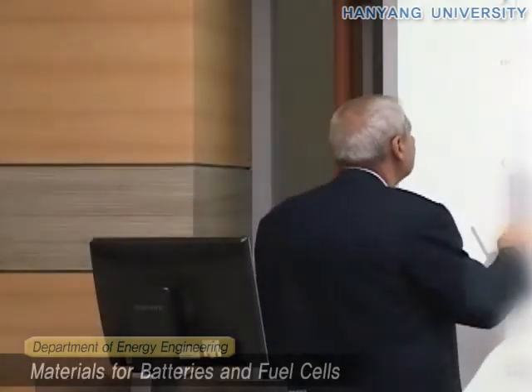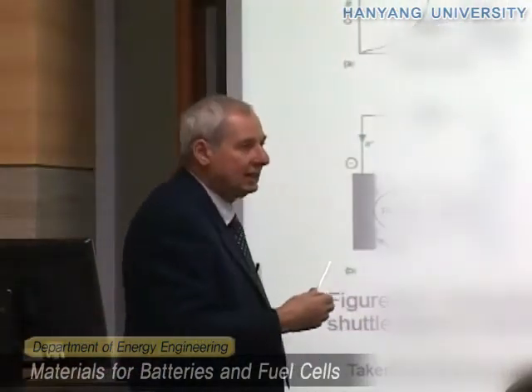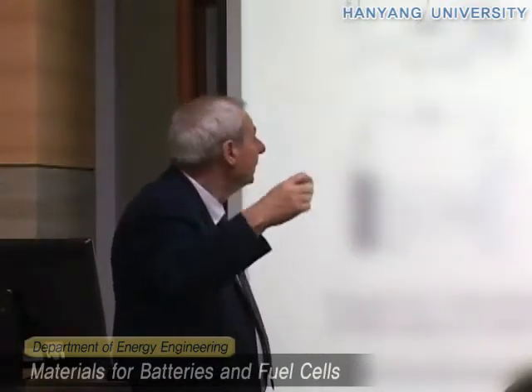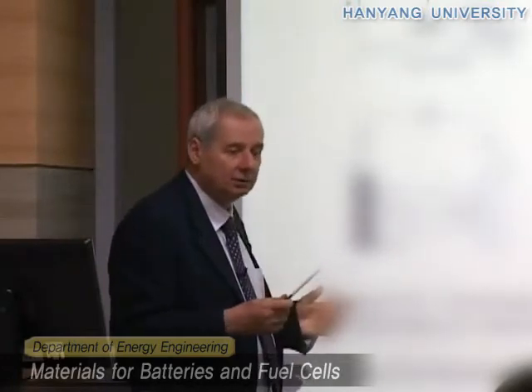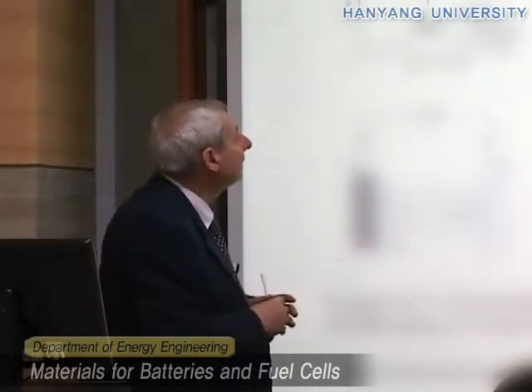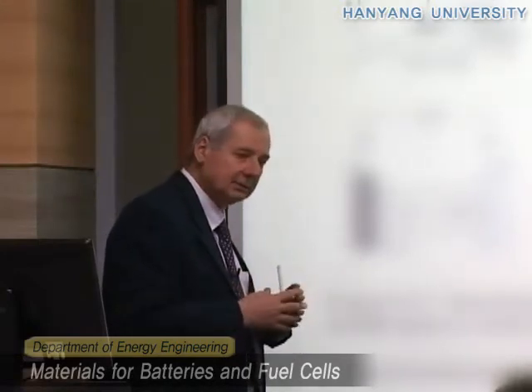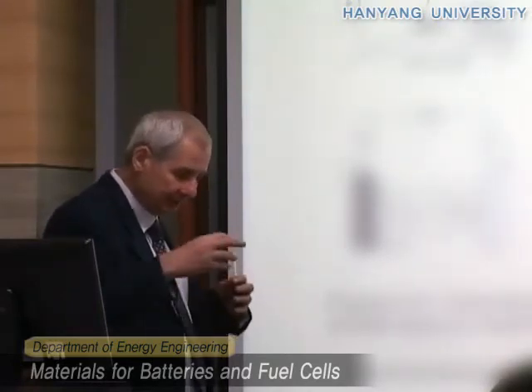The decomposition of the electrolyte is so bad because suppose that during charging of a battery the voltage rises and goes to 4 volts. You have some decomposition of the electrolyte — either the solvent or the salt. This creates some gas. And suppose there is some local heating in the cell, maybe due to excess charging or very high current — the electrolyte will take fire, or the thermal effect will propagate through the electrolyte. This is called thermal runaway, and finally the battery explodes.